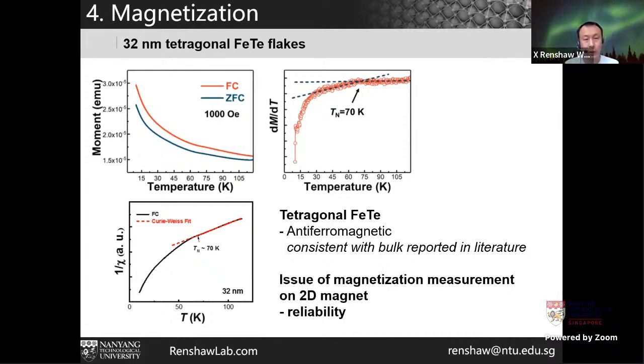For example, the magnetic properties. Now to measure the magnetic properties, we naturally go directly for MPMS or the magnetization measurement, or you can call it a magnetic moment measurement. We did ZFC and FC, which is zero field cooling and field cooling, to see the magnetic behaviors as a function of the temperature. This is a 32 nanometer thick tetragonal FeTe, which is relatively thick. Of course, the flakes are all around the substrate. Initially we thought we could capture the magnetic property easily. Now it turned out that the result is not very clear.